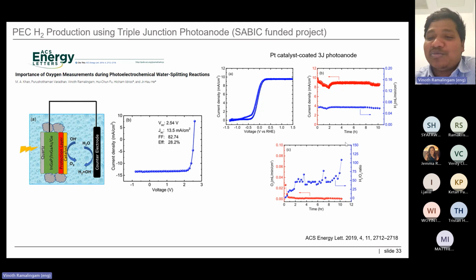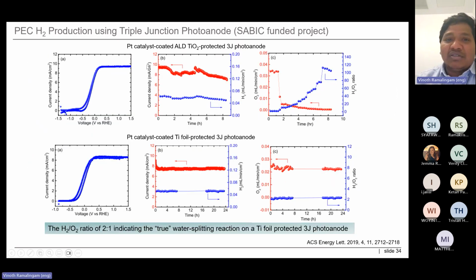Then we realized that this is not a water splitting reaction. Something is happening, because instead of splitting the water, the semiconductor itself degrades and it produces the current density, but it's not a water splitting reaction. So to further evaluate that, we coated 40 nanometer of ALD TiO2 on the protected triple junction photoanode.